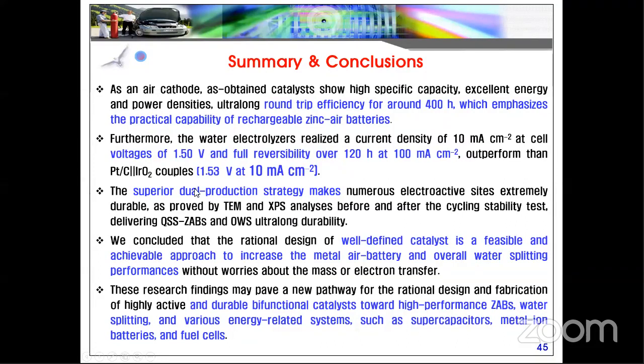And with this strategy, from the studies, I conclude the core-shell structure is one of the challenging, because when we are making the core-shell materials, we can protect the active material from degradation and enhance the stability, and that material can be used for the ORR, OER and HER. Finally, we can fabricate the air battery and water splitting devices.